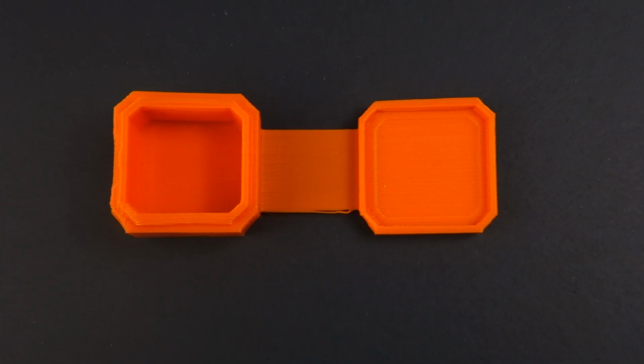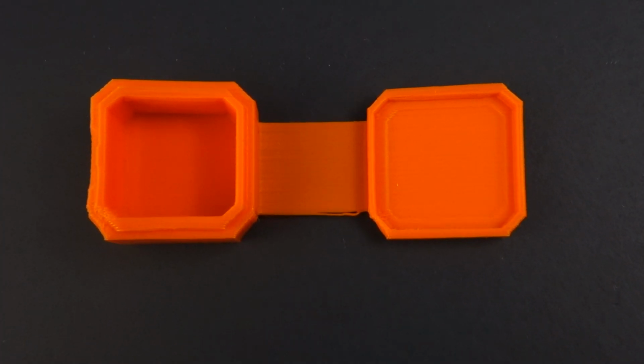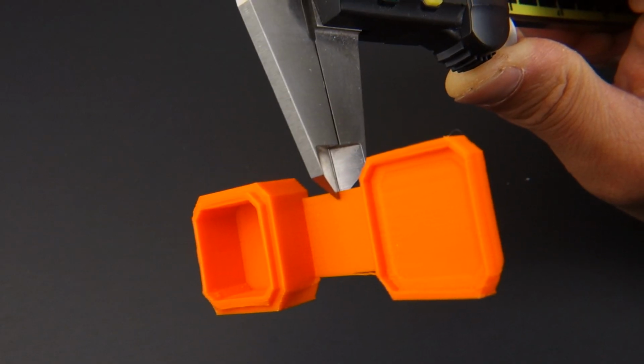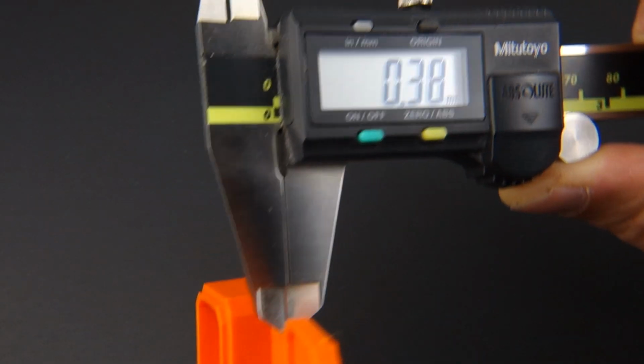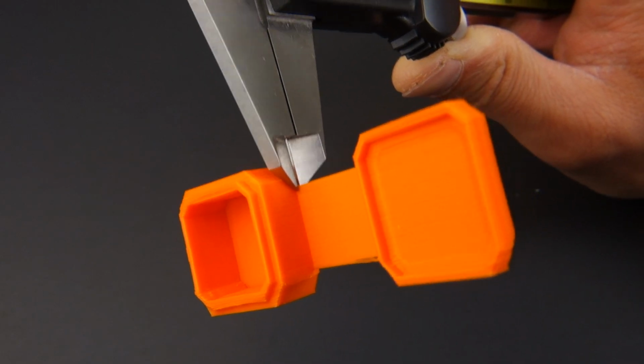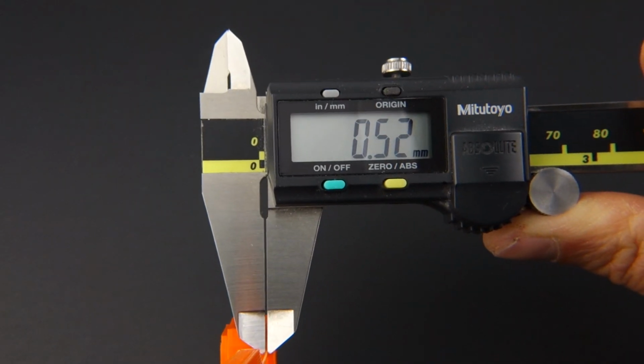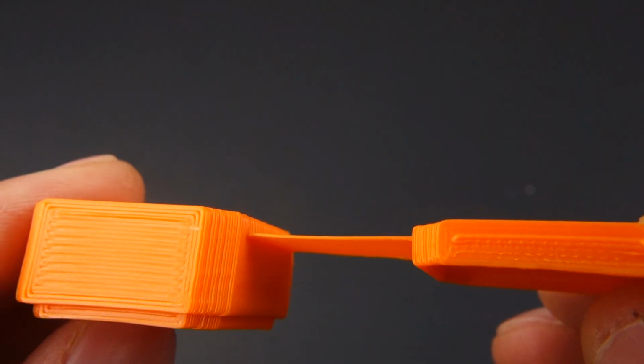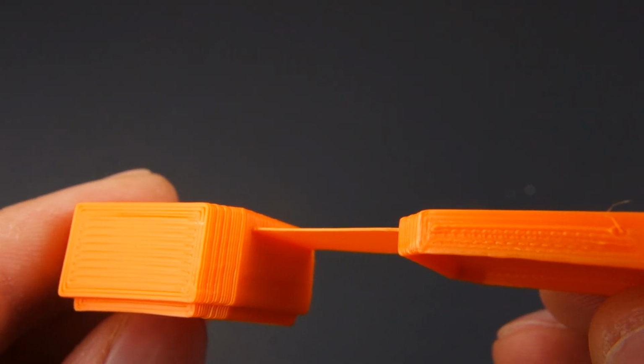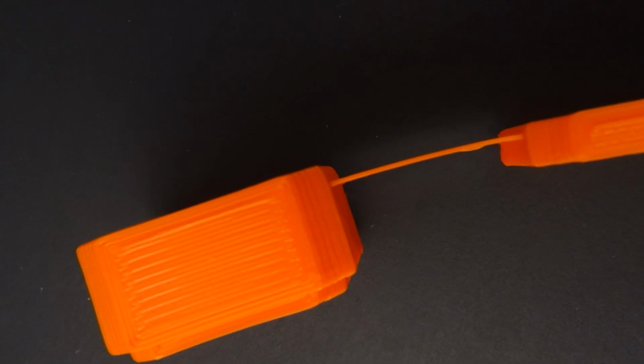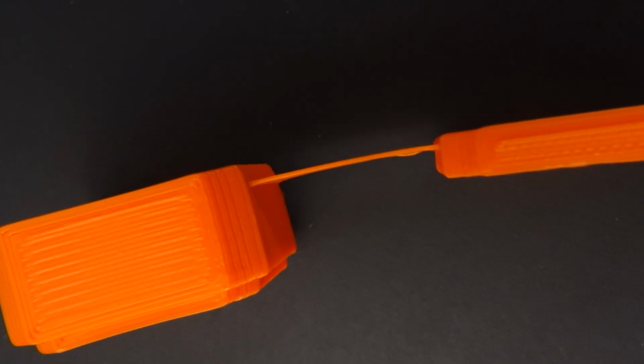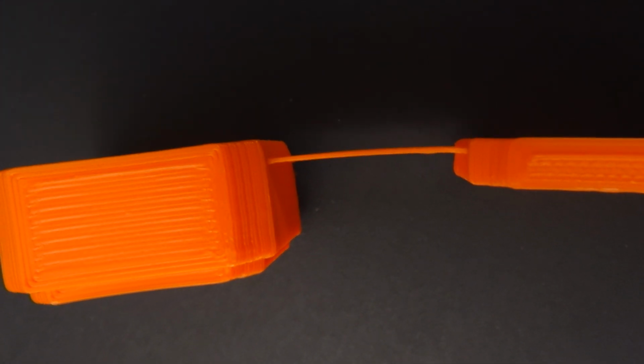And the hinge looks amazing. All of the gaps are gone. So let's measure the hinge thickness in the middle, and it comes out to be 0.38 millimeters. And now on the left side of the hinge, and it's 0.52 millimeters. So the start of the hinge is a little thicker than in the middle, but the small amount of widening at the edge is actually good. It will help absorb the higher stresses at the joint.